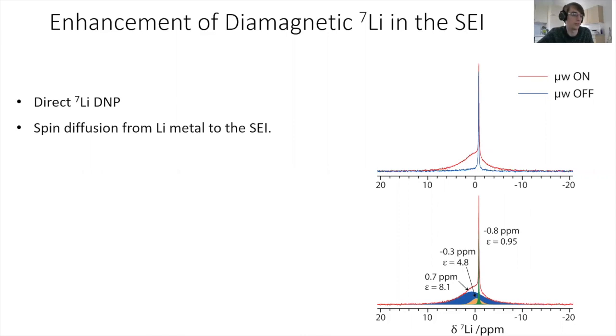Because we do have some anisotropy of our interactions and we're under magic angle spinning conditions, you can still get spin diffusion, I think, for that reason. The other possibility is that you have diamagnetic lithium that's sufficiently close to the metal surface to directly interact with the electrons and undergo DNP directly. And so I've said spin diffusion in my slide, and that's maybe not a definitive answer.